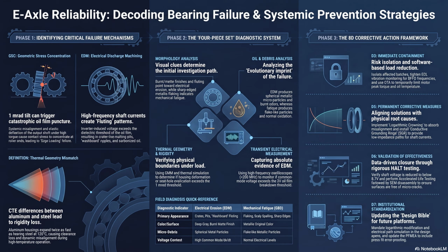Right. It's absolutely proof. But they don't stop there. Piece 3 is thermal geometry. They put the empty aluminum housing on a CMM, a coordinate measuring machine, a very precise robotic probe. It creates a flawless 3D map. If it shows perfect alignment at room temperature, but the bearing has that washboard fluting and melted debris, it firmly points to electrical erosion. The geometry is sound, so electricity is the culprit.